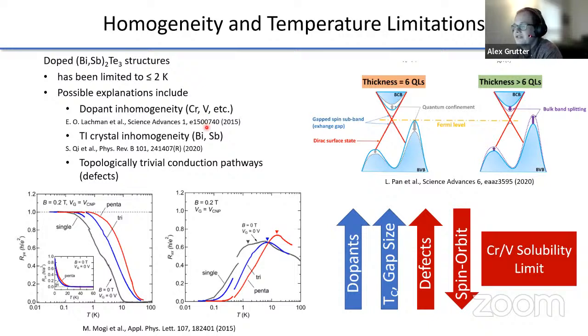You also have to worry about preferential substitution of your magnetic dopants on specific sites, and also topologically trivial conduction pathways. And here it's sort of helpful to look at this really nice diagram from Pan et al., where they were trying to understand where this suppressed quantization temperature comes from. And one of the things that they pointed out is that the actual shape of the valence band and the conduction band is kind of complicated. And if you're not really careful with your structure design, you can get cases where the bulk band actually overlaps with the gap in the surface state. And so the Fermi level then passes right through the bulk band all of a sudden, and then your topologically trivial conduction pathways dominate. And this can also happen if you get a lot of dopant-induced defect conduction states that are sitting right in the middle of the exchange gap as well.